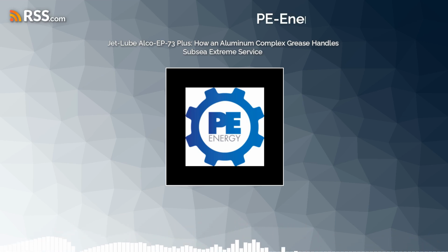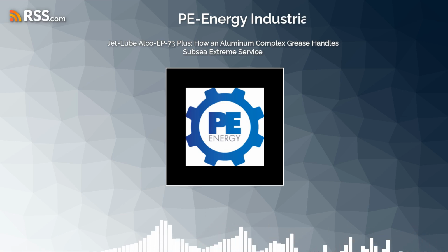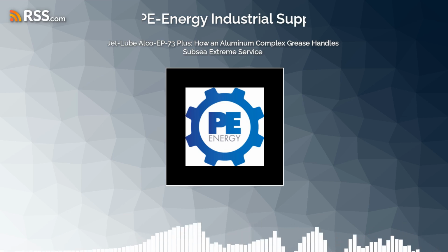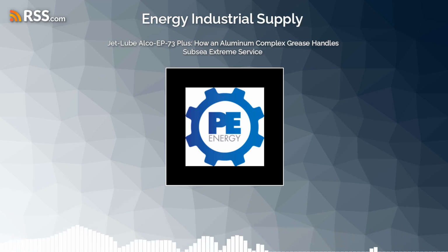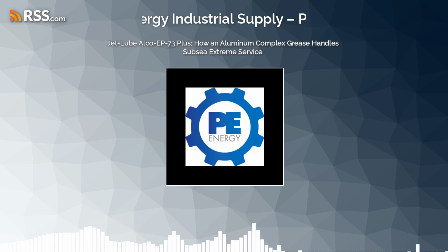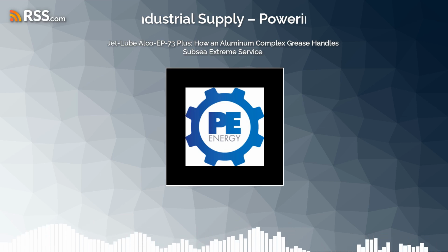Oh, wow, okay. Yeah, and the sheet backs that up with a penetration rating of 265 to 295 at 77 degrees Fahrenheit, which is measured under the ASTM D-217 standard. Wait, that penetration test involves dropping a weighted cone into the grease, right? Exactly. And the deeper the cone sinks, the higher the number, meaning a softer grease. Precisely. By engineering it to hit that 265 to 295 window, they ensure the lattice structure is firm enough to stay exactly where a mechanic applies it.